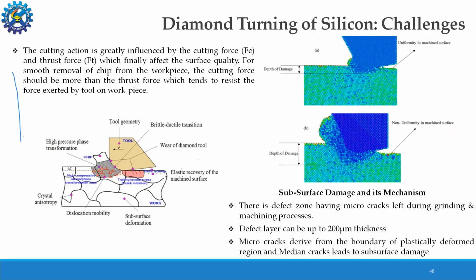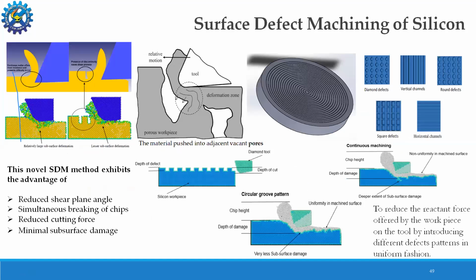Further, we are also studying subsurface damage detection by using molecular dynamics simulation, like what is the depth. Till now we were associated with only the surface finish, but there are certain cracks which propagate beneath the surface. Measuring those cracks is very difficult, and this is the most essential requirement of any optics, because if cracks are present, then that optics cannot be used at different temperature and pressure conditions. Like we are talking about aircraft, the pressure and temperature conditions are entirely different from normal conditions. So if any cracks are present, then it will lead to the breakage of optics. So we are also into the determination of subsurface damage by using various modeling techniques and characterization tools.